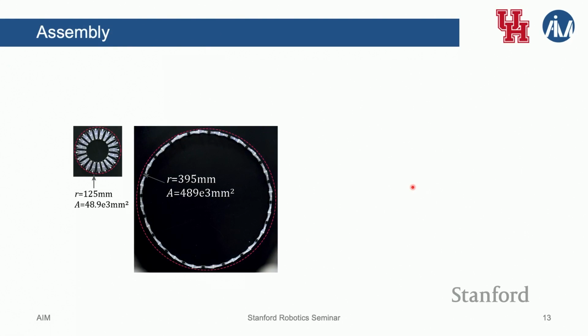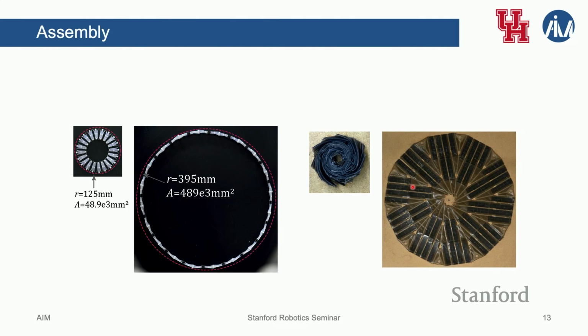And now we have the ring and we have the origami, both 3D printed with the same material, as a matter of fact. So everything that you see that's darker, so the entirety of this and the joints of this, are shape memory polymers of the temperature we intend for it to operate on. The white stuff is also a shape memory polymer, but it transitions at a much higher temperature. So we can, for our purposes, pretend it's not reacting in that way.